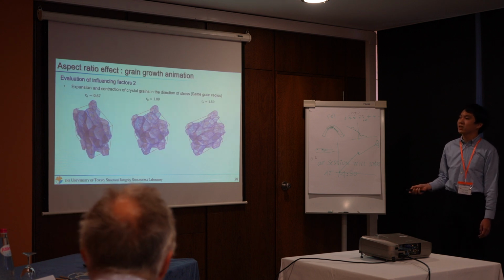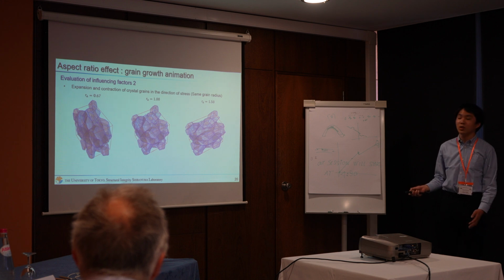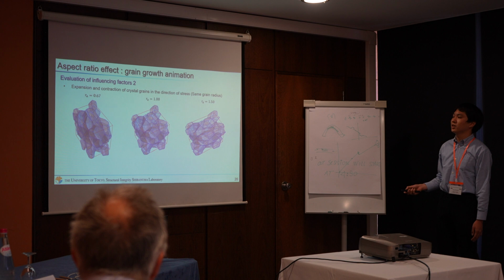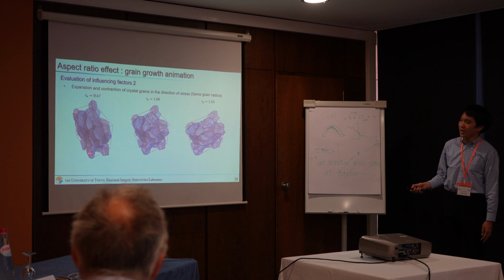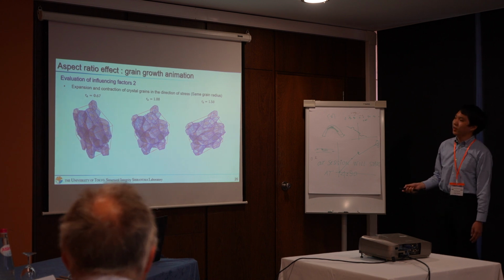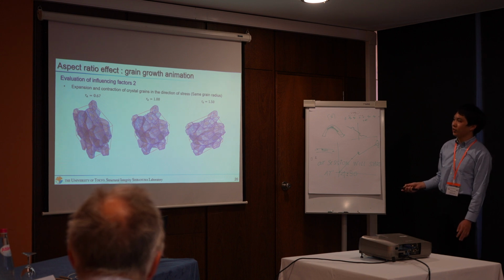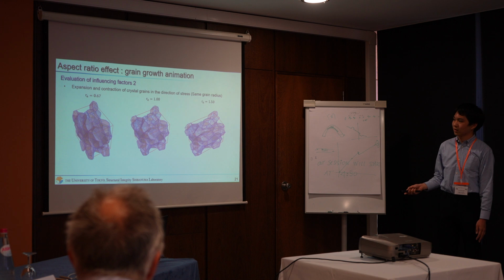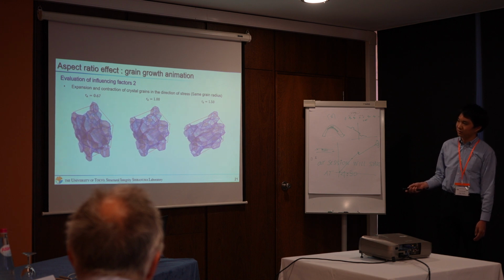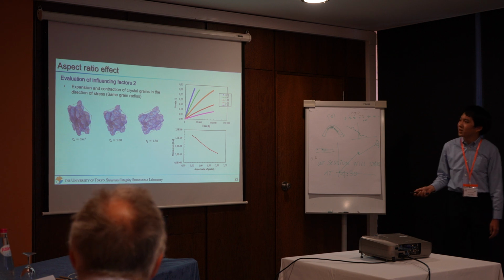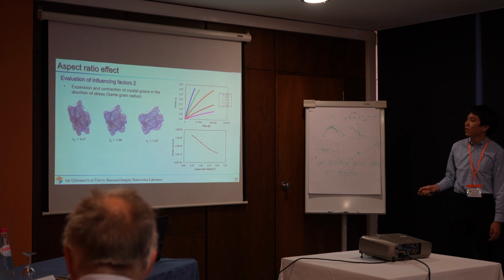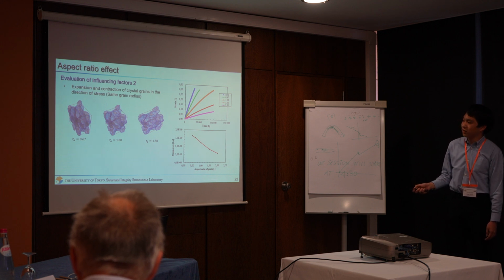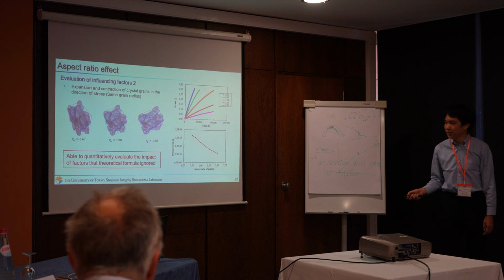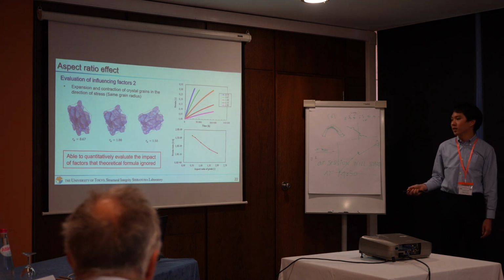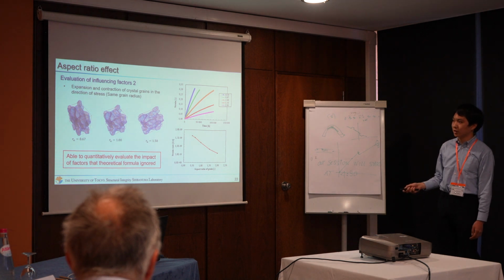And next, we changed other influencing factors that cannot be considered in the conventional theoretical formula, such as aspect ratio. For example, we expand or contract the grains in the direction of stress under the same grain radius. And this is the result. According to the aspect ratio, the strain rate differs. So we can quantitatively evaluate the impact of factors that the theoretical formula ignored.